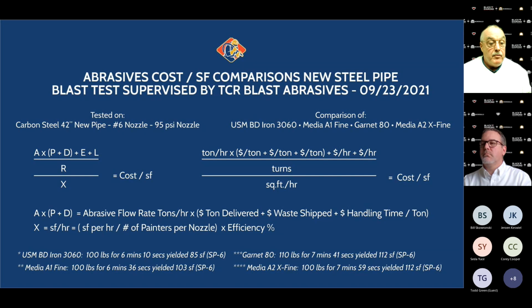So before we leave this slide, there have been some questions. The carbon steel, all 42-inch new pipe, is a number 6 nozzle, and we had 95 pounds of pressure on the nozzle. Those are all measured. Those are all known quantities. We tried to eliminate variables in order to reduce it down to the 3 variables: the weight, the amount of material used, the time it took to blast, and the square footage that it covered.